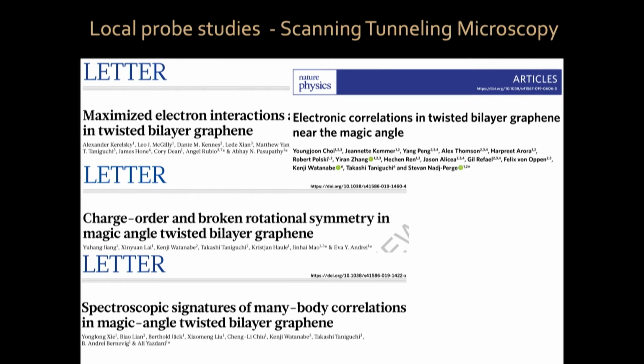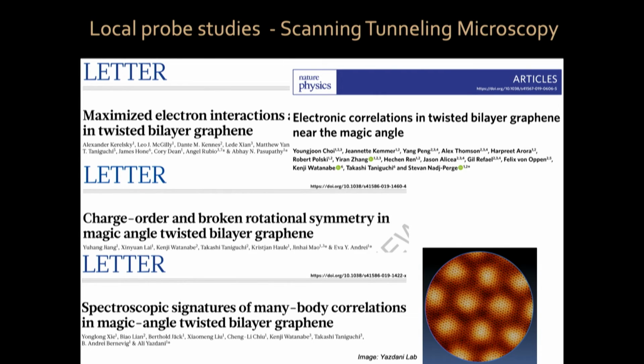This system is a very strongly interacting system, and electrons do very weird things, which they don't do when you investigate regular materials like monolayer graphene. And in particular, in all of these systems, they were able to image directly. This is the Moiré pattern, those AA sites, those bright spots, and you can see the atomic lattice underneath it. And they were able to image exactly what happens with the wave functions of the electrons in this system, which was very interesting.